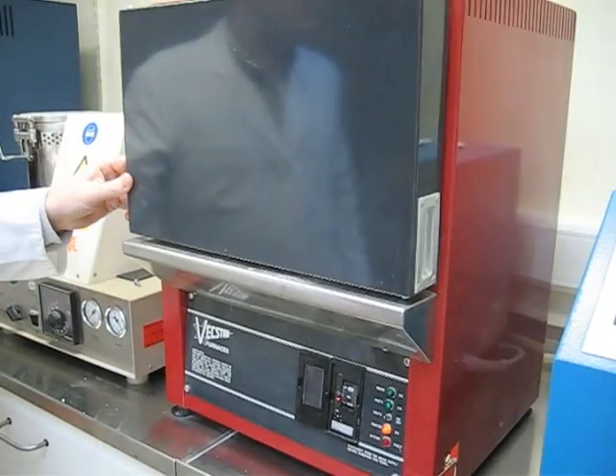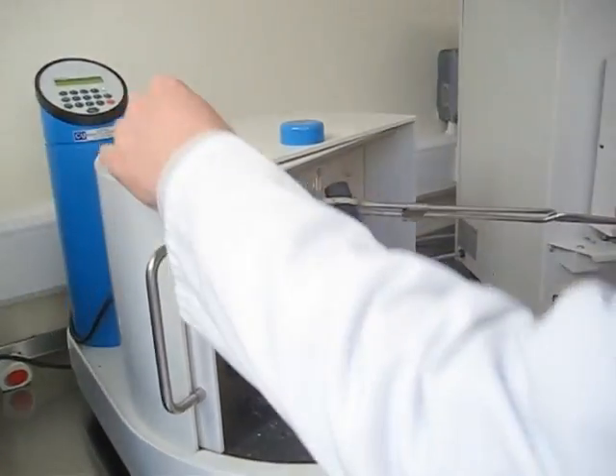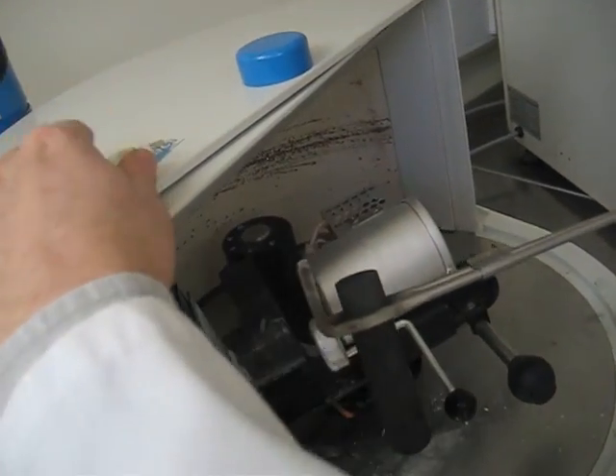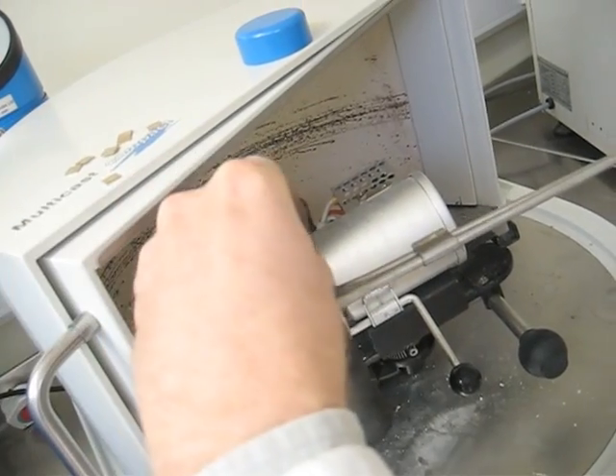That's set for about half an hour and then into the furnace at about 650 degrees. It goes up to 650 degrees and it heat soaks in there so it wants to get up to temperature and then be in there for another 45 minutes or so.